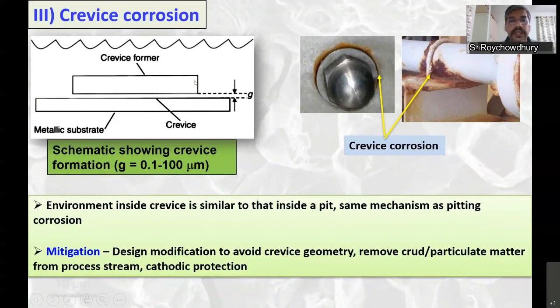If it is too open, then it will get flushed very easily by the outside environment and crevice corrosion will not occur. Why does flushing prevent crevice corrosion? Because the environment inside the crevice is similar to that inside a pit, with the same mechanism. So any flushing or flowing conditions will prevent crevice corrosion.